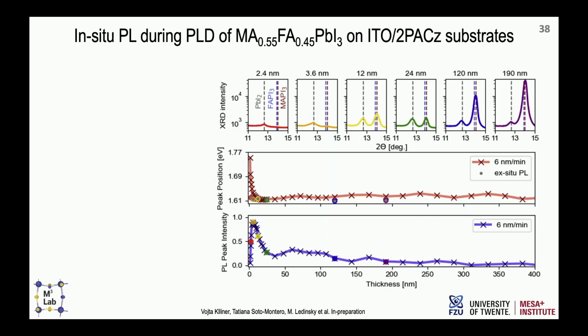So what is happening is we already know how the film is growing from the GIWAXS I showed before. But what we see here is, on the x-axis the thickness, and on the y-axis the peak intensity. And we notice that at the beginning of the growth, the PL is very strong, and then afterwards it goes down and stabilizes. Also you see that the bandgap is changing at the beginning, and then it becomes very stable, around 1.6 electron volt, which is the bandgap of the perovskite.